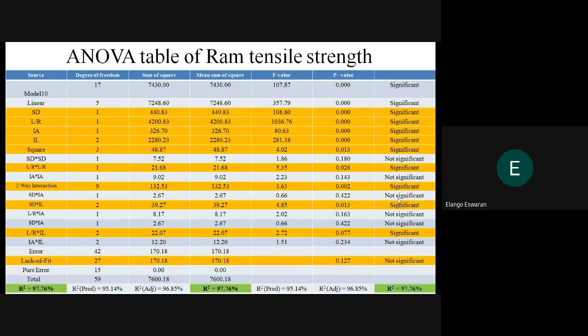It is witnessed that all the chosen parameters hold a significant effect on the response, with respect to the square of the SS and interlayer, and the interaction effect of standoff distance and interlayer, and loading ratio and inclination angle. The p-value for the regression model is lower than 0.05, that is 95% confidence, which indicates the statistical significance of the developed model. The correlation coefficient R square was 97.76, which indicates 97.76% of the variance is considered in the regression model.